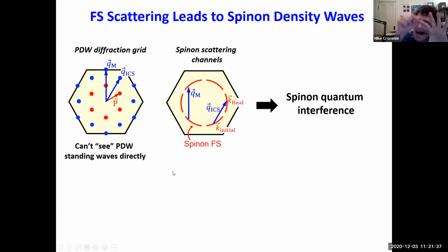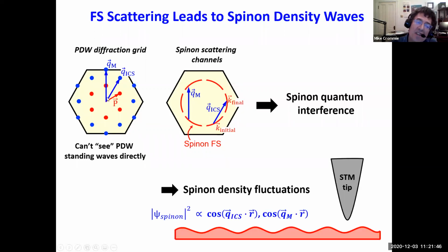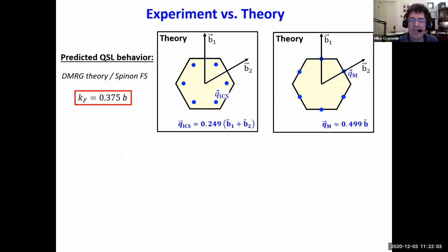So we'll get scattering within the Fermi surface of the ungapped spinons, and that will lead to quantum interference at precisely these wave vectors of the scattering potential, the QM and the QICS. That leads to quantum interference density waves in the spinon density that we should see with the STM, and that's what we believe we're seeing. And so from this treatment, you get very specific predictions of what wave vectors you should see in the spinon density.